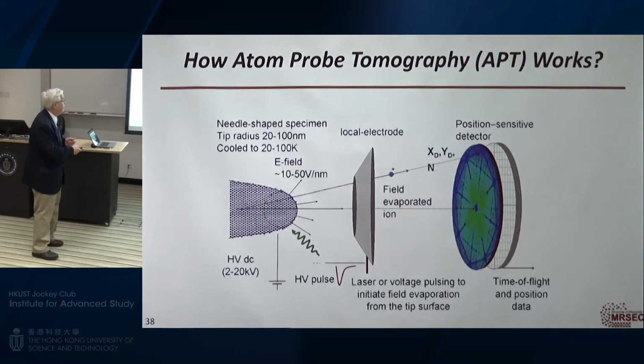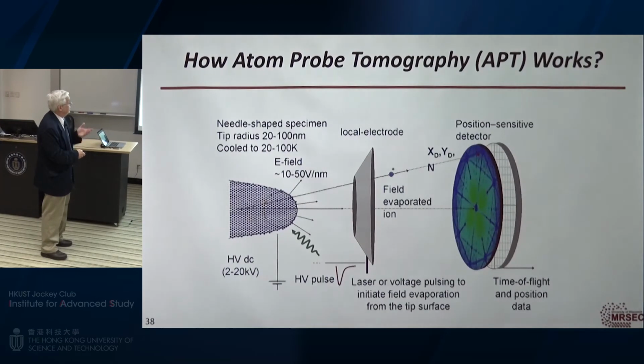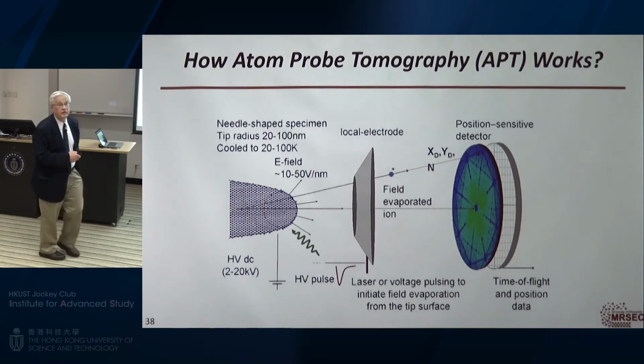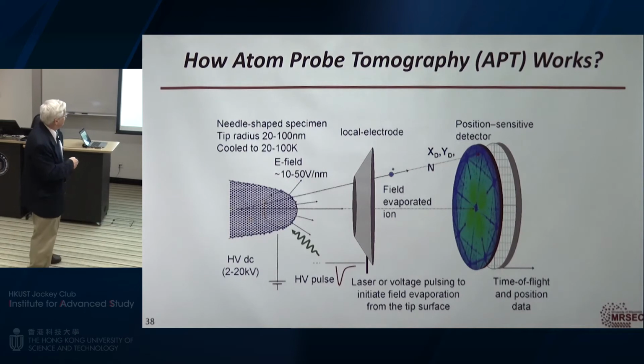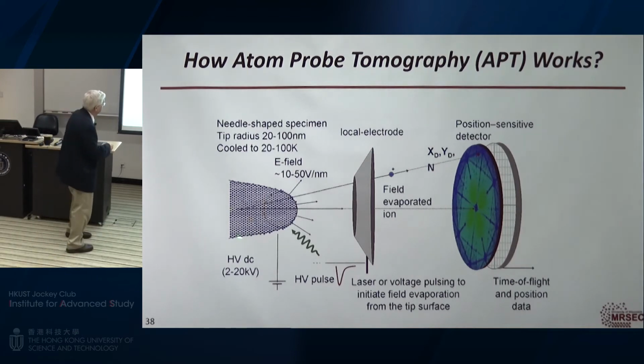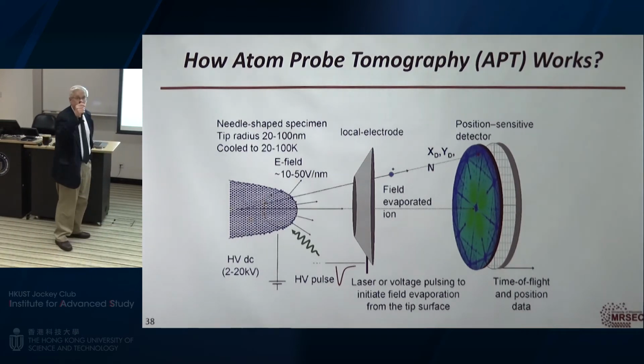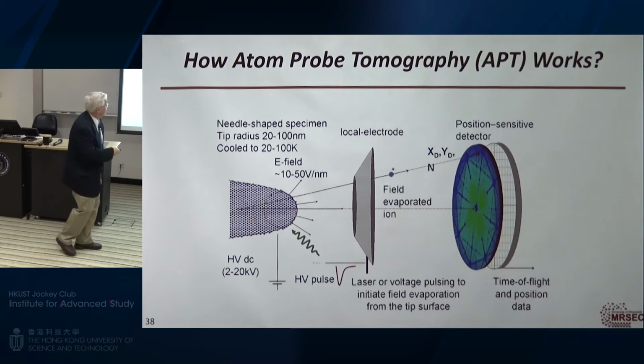We wanted to understand that in a little more detail, so we use other techniques to look at that. One of them is atom probe tomography. This is a newer technique, which is actually quite exciting. What it does is you take and make a needle out of the material. We have that film, and we use a focused ion beam to make a very, very sharp little needle of the material.